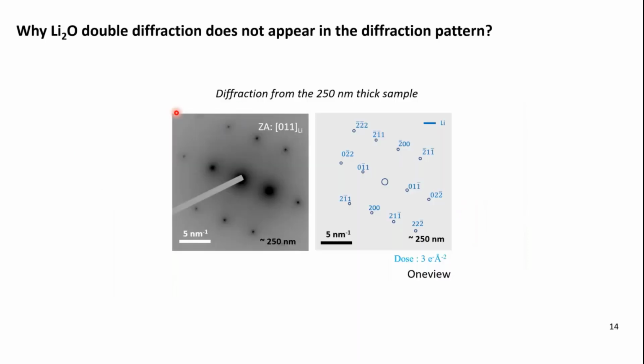All right, let's go to some interesting part where we can use a direct electron detector to detect very subtle and weak diffraction patterns. If you happen to remember the diffraction patterns of the thick lithium lamella, we didn't see lithium oxide diffraction patterns or even double diffraction, although we did see some lithium oxide in the thin sample. So we have a few hypotheses regarding this observation, but after taking diffraction patterns with the Metro camera, things got much more straightforward to understand.